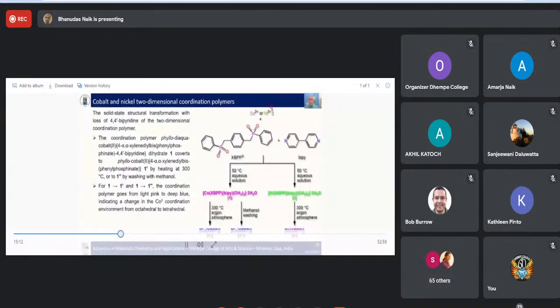And the second set of coordination polymers are these cobalt and nickel compounds. So beginning with cobalt and nickel ions here, if we react with the ligand, usually you form a salt, the ammonium salt of this to begin with, and we use the acetates here. So then you have ammonium acetate, which if you just heat them up, they'll all just evaporate out of the solution. And also we made a third ligand here, 4,4'-bipyridine, to have a spacer to connect between the metal centers. And actually this worked out well.